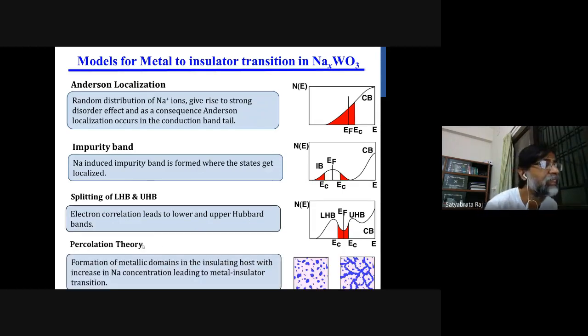Or you can check that percolation theory can also explain a metal-insulator transition. Let's say this pink color is your WO3. As soon as you put sodium, any amount, that becomes NaWO3. NaWO3 is metallic, and this blue becomes NaWO3, a cluster of NaWO3 spread over your WO3 matrix. As you increase your sodium concentration, you may get a channel going from one end to the other, and when you do resistivity, it gives a conducting path, and the system can behave like a metal. But this implies that you have a metallic phase and also an insulating phase.